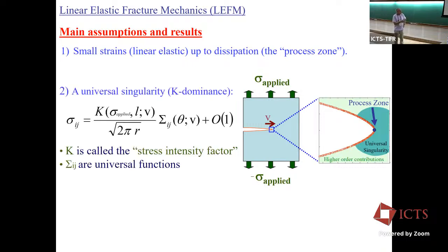Okay, now, if you solve the problem, again, solve the two wave equations with these boundary conditions, stress-free and displacement boundary conditions in front of the crack, this is what you get. Like Inglis showed by squashing the ellipse, you get the same solution. You get a singularity that goes like 1 over the square root of r times some factor, which is dependent on the applied stress, on the instantaneous length of the crack, and on the crack's instantaneous velocity, times some universal angular function, okay?